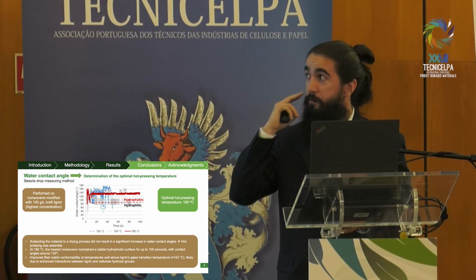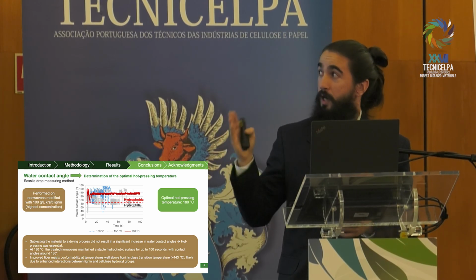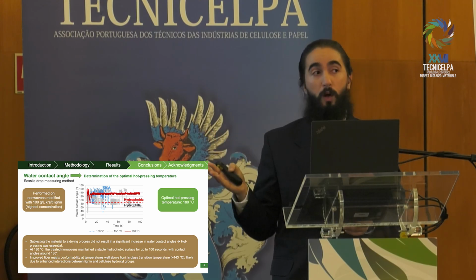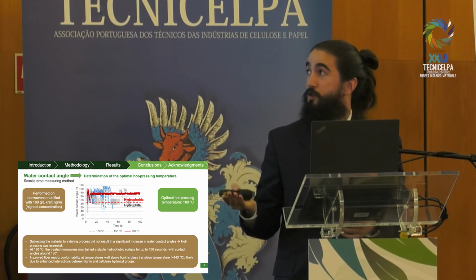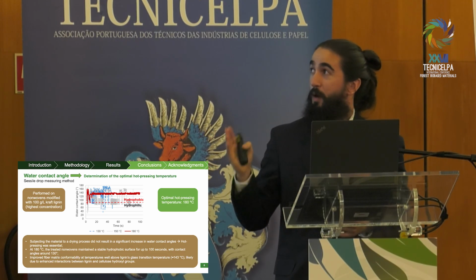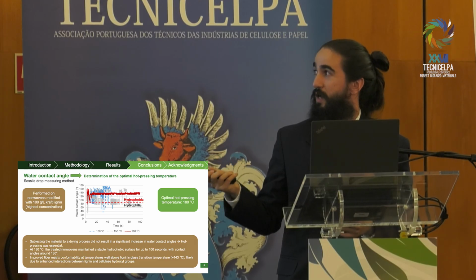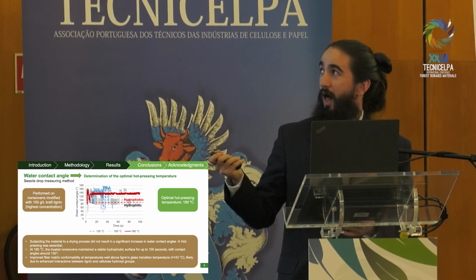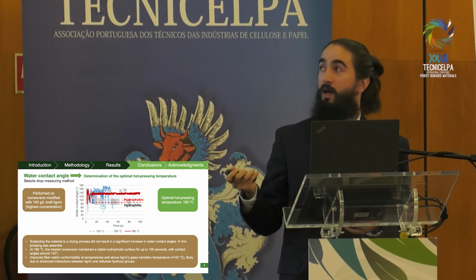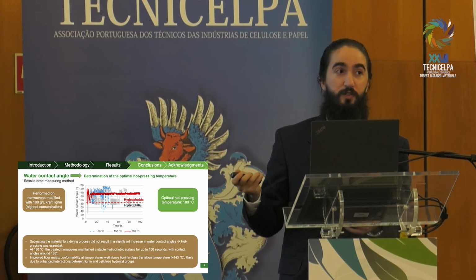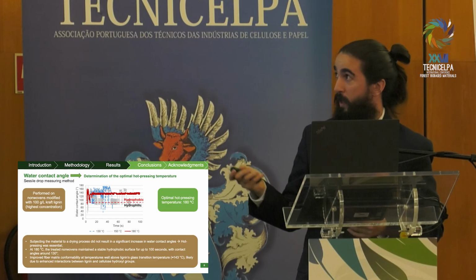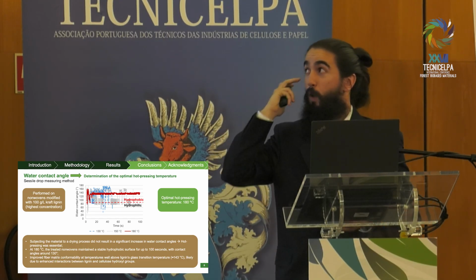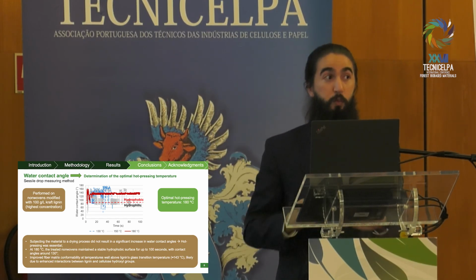And as you can see, with 130 and 150 degrees, we could not obtain very stable results. Sometimes it worked, sometimes it didn't. But when you use 180 degrees, as you can see, almost up to 100 seconds, around 130 degrees of water contact angle. So it's clearly hydrophobic. But how can I explain this? Why at 180 degrees it works?